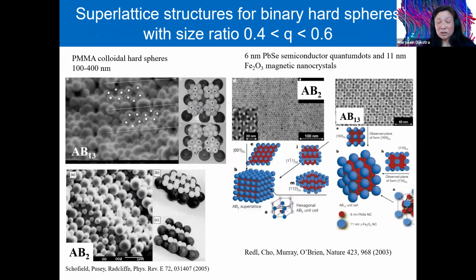One of the most exotic crystal phases is the AB13 crystal phase, where the big spheres are sitting on a simple cubic lattice, but at a distance so far apart that an icosahedral cluster of small spheres fits perfectly in between this simple cubic crystal structure. And these icosahedral clusters are rotated by 90 degrees with respect to their neighboring clusters. Another crystal is just the AB2 crystal.